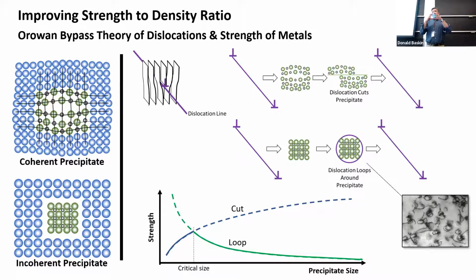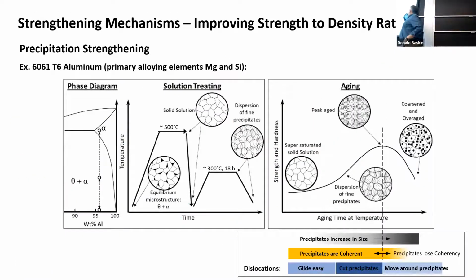If the precipitates are big, it's energetically favorable for the dislocation to loop around the precipitate. And this is what that actually looks like under a transmission electron microscope. There is an optimum. Once you get to the point where the dislocations are looping around the precipitate, the increase in strength decreases. The bigger the particles get, the more looping, and the strength of the material goes down. So there's an optimum size, where you're growing these tiny little precipitates, a couple nanometers, getting a little bit bigger, and they hit a point where they're the exact right size that they're causing the most difficulty for the dislocation to cut through them. See that? So this point right here, this point is where you get the most strengthening.